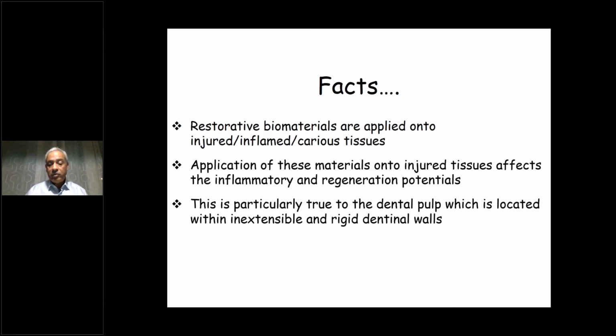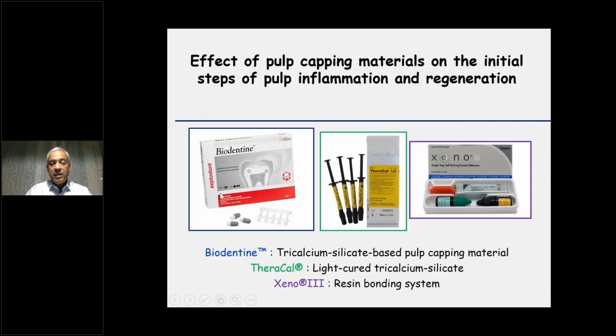So what we did to understand this is that we selected three types of materials. Of course, we used Biodentine that we know very well. Then we used a resin bonding system, Xeno, and we used a mixed material that is a light-cure tricalcium silicate, for different reasons. This represents a kind of step in between tricalcium silicates and resins. And we wanted to see if there is any effect of these materials on inflammation and regeneration.